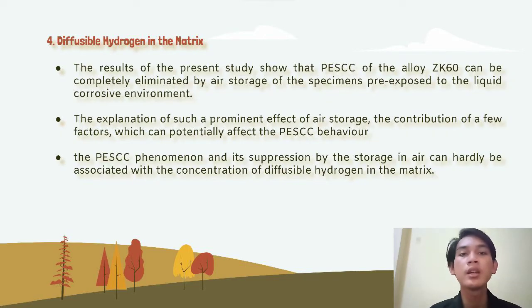4. Diffusible hydrogen in the matrix. The results of the present study show that PESCC of the alloy ZK60 can be completely eliminated by air storage of the specimens pre-exposed to the liquid corrosive environment. To explain such a prominent effect of air storage, the contribution of a few factors which can potentially affect the PESCC behavior is considered. The PESCC phenomenon and its suppression by storage in air can hardly be associated with the concentration of diffusible hydrogen in the matrix.